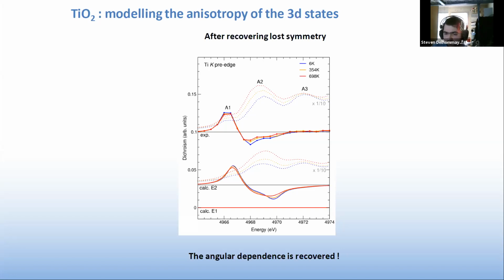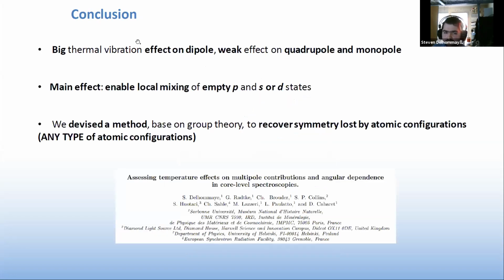And so, for a rapid conclusion, in this study, we could get a global overview of the effects that the thermal vibrations have on the different multipolar contributions to this kind of spectra, and the main effect was on the dipole part by enabling local mixing of np and s or d states, whether we're looking at XAS or XRS. And we also devised a method based on group theory that allows us to recover the symmetry that is lost when we use atomic configurations.